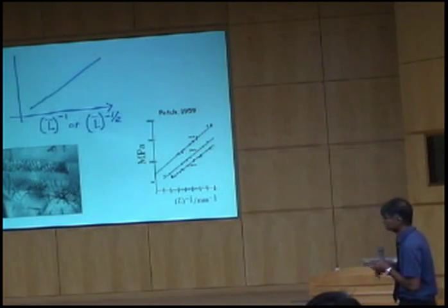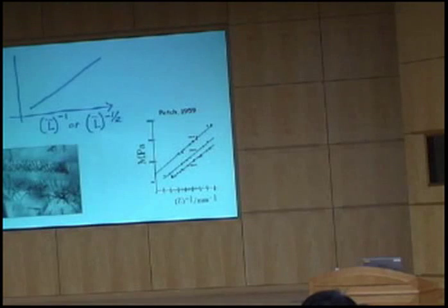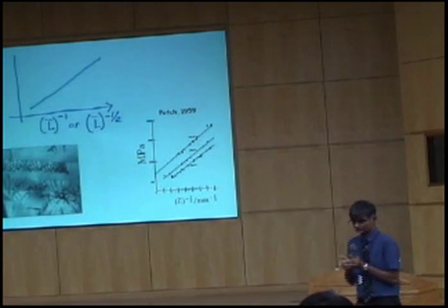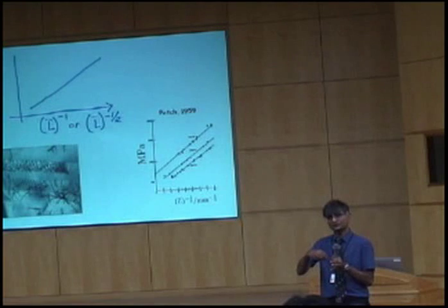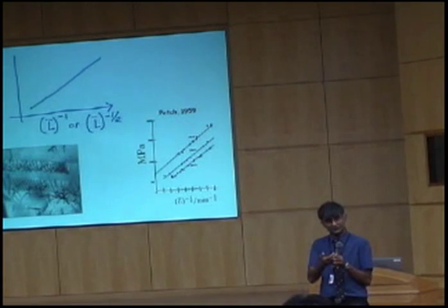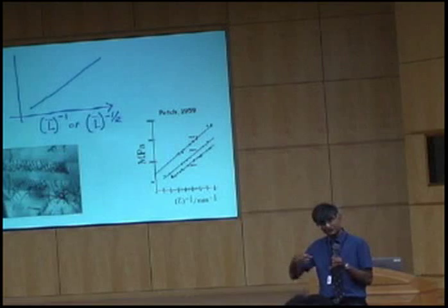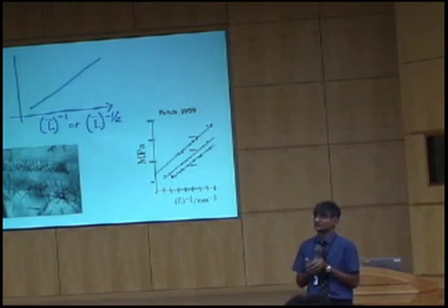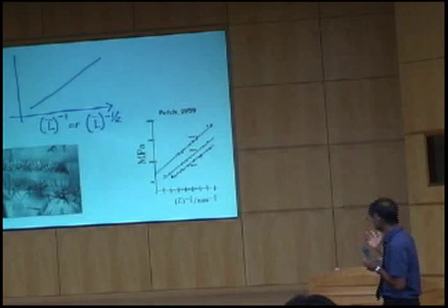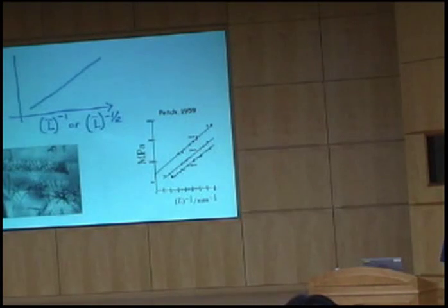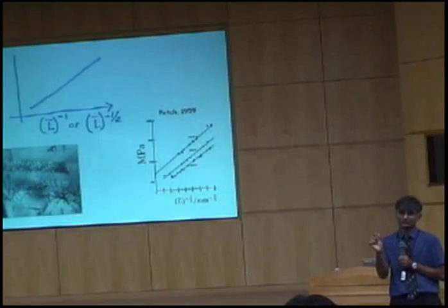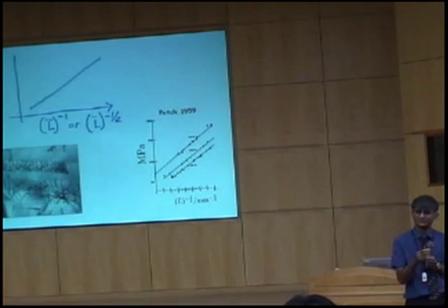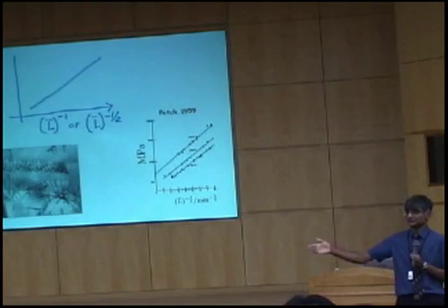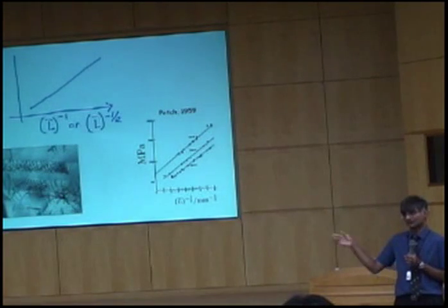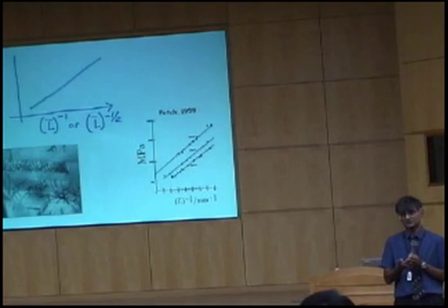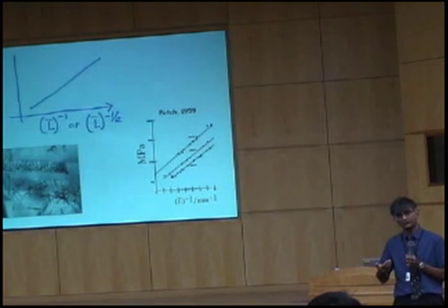And that mechanism works when the grain size is reasonably large. But when the grain size becomes very small, there are no dislocation sources present inside the grain. And it's really dislocations in the boundaries which have to move in order to propagate plasticity across grains. And then when we talk about martensite or bainite, the plates are very thin, you know, of the order of a quarter of a micrometer in size. So what's controlling plasticity propagating across grains is not the Hall-Petch mechanism, but dislocations in the boundaries which have to move across the grain.